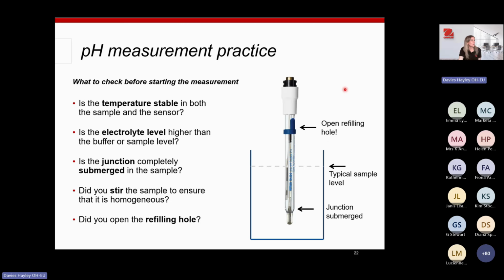Just double check when you are measuring the sample. Is the temperature stable in the sample and the sensor? Is the electrolyte higher than the level of the buffer or sample level? This means that if your sample level is here, you need to make sure your electrolyte is higher than that sample level. Is the junction completely submerged in the sample? Did you stir the sample to make sure that it's all nice and homogeneous? And did you open the refilling hole? When you have a refilling hole, it's important to open it once it's in the sample, to make sure that the electrolyte can flow out of the junction.